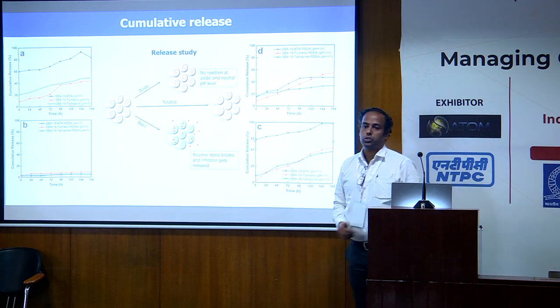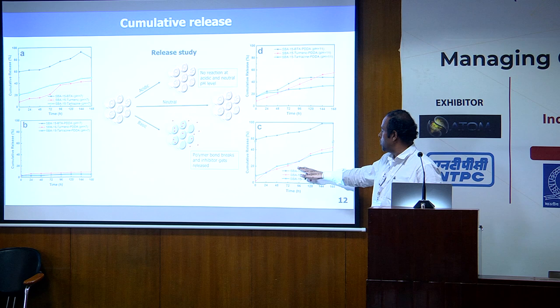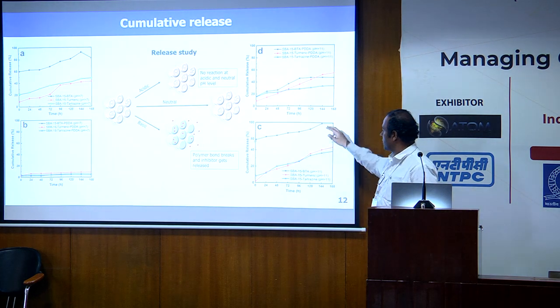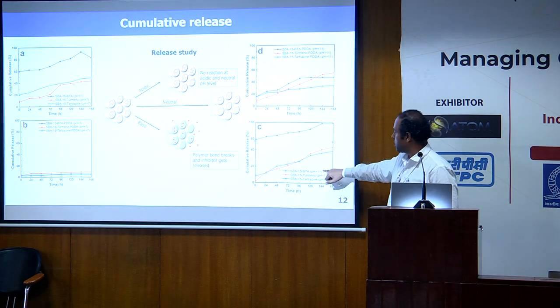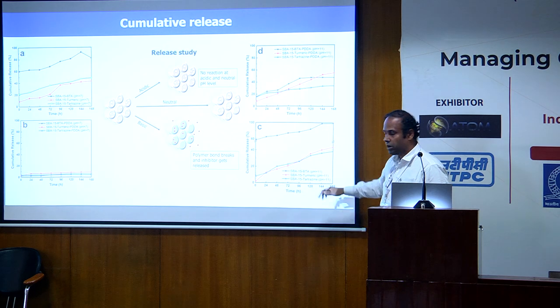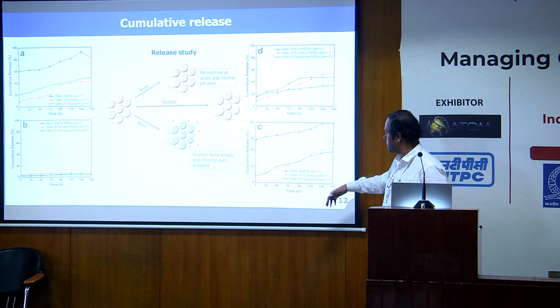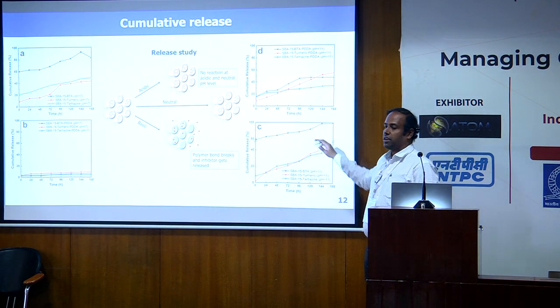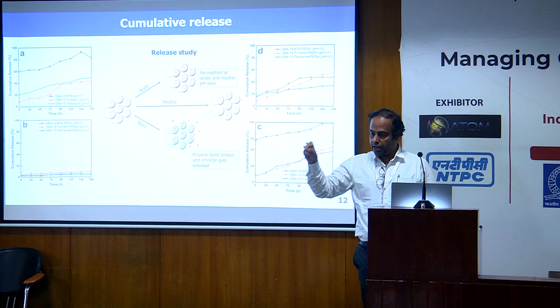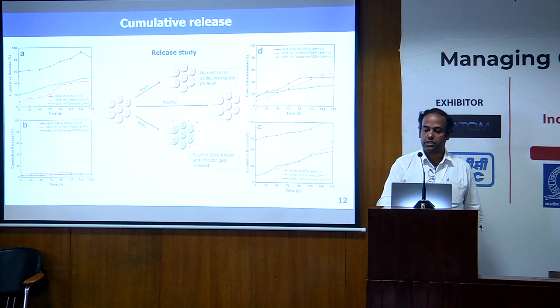Now you bring it to pH 11, and we check that we can have a slow release over a period of time. This is for three different inhibitors we tried. One is BTA as a benchmark, turmeric, which is a green inhibitor, and tartrazine. So we found out that it has a slow release, compared to just direct dispersal of these inhibitors.